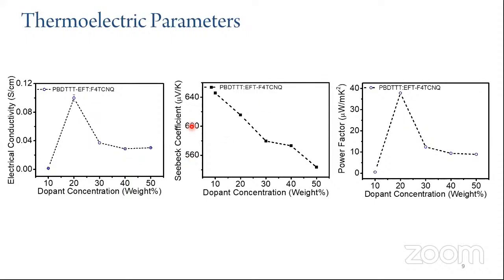And the p-type doping is confirmed by the positive Seebeck coefficient values, and upon increasing dopant concentration, we can see that the Seebeck coefficient decreases, that is from 645 to 542, leading to a maximum power factor of 37.4 at 20 weight percentage of dopant.